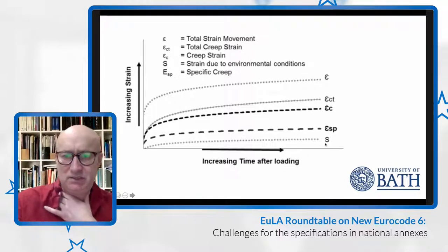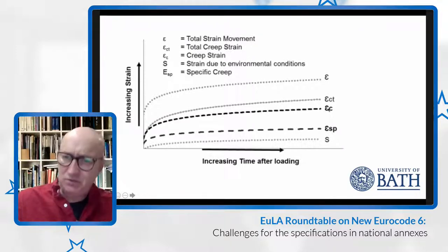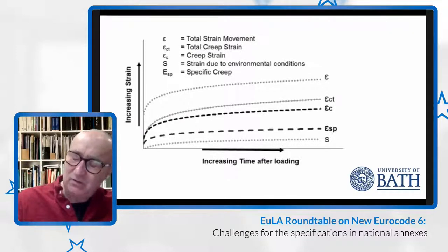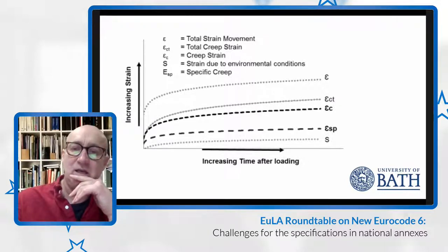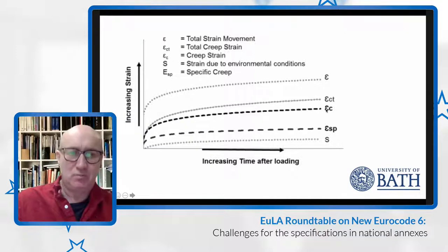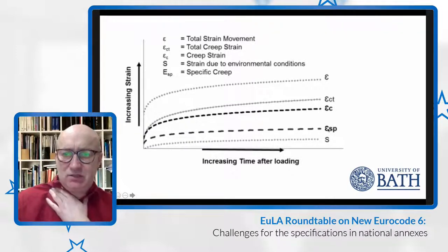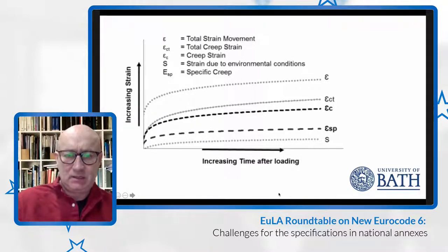And so we deducted the shrinkage strain to get the total creep strain here, which would have been, as for the case of the masonry wall test, and the creep strain we reported would be the same as the specific creep strain because the stress levels were the same. So hopefully that provides some clarity to what we tried to do.